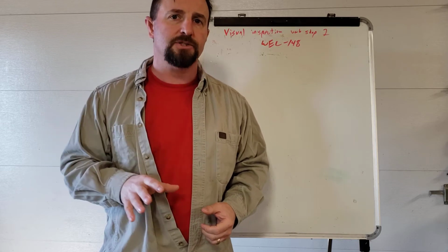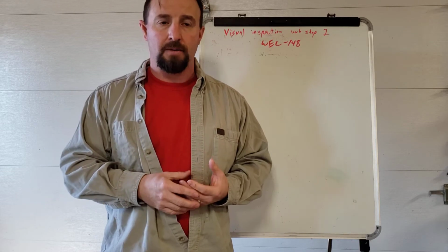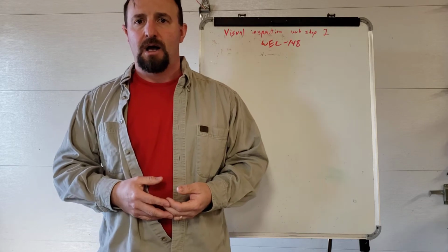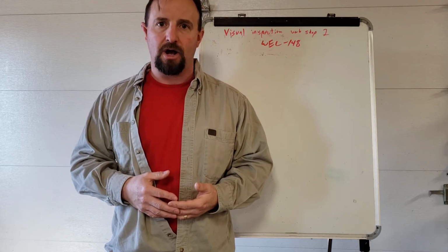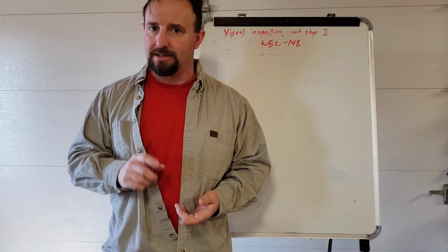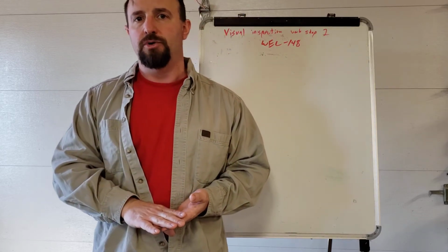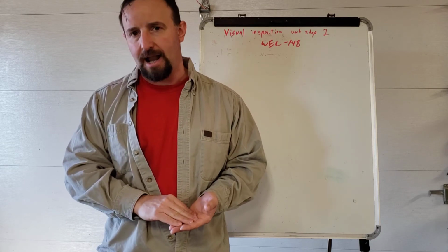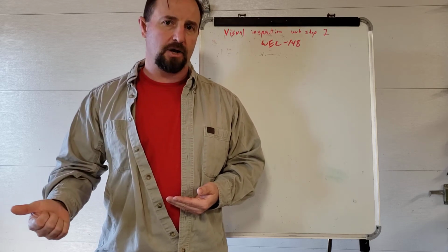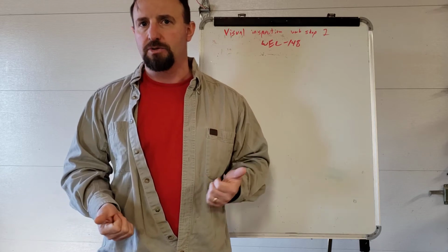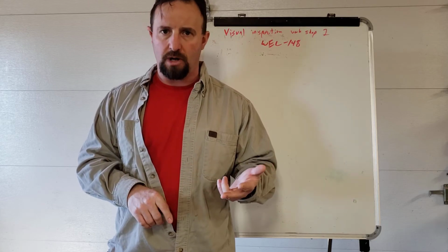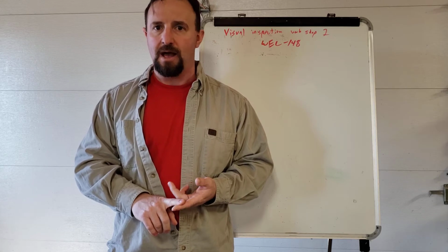This will end up causing you to have things that just don't work. They may kind of look good, but there's no fusion there. That weld is just sitting on top of the metal, and you might even be able to knock it off. You guys saw this a lot when you're doing your vertical downs, because that weld just sits on top. That is a classic example of lack of fusion. If you're doing this on a multi-pass weld, that can happen as well, where just one pass doesn't fuse with the others. One of the other reasons that can cause this is being in the wrong polarity, especially with hardwire welds. If you're supposed to be welding in DCEP, which is where most of our hardwire welds are, and for some reason you're in DCEN, that weld will not bite.